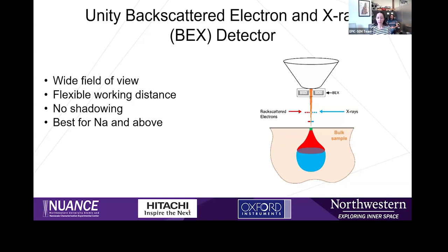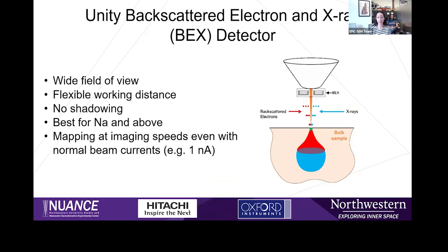So a big thing with this detector is it's not just that it's great for mapping, it's fast. You can actually map your sample at basically normal imaging speeds. So you can get basically full color images with compositional information in real time. This is going to make it a lot easier to find rare phases of interest because you can basically just move and scan around your sample and search. Just look for that color difference and find your region of interest.